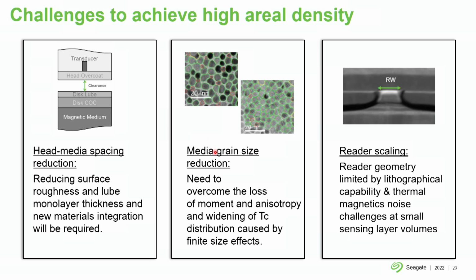Harped about grain size reduction. We have demonstrated 5 nanometer grain size, but it's also a matter of ensuring the distribution and properties are tight, and also the distribution in grain size is tight. And again, that's a very active research area in our recording media design center. And reader scaling is perhaps one of the more concerning issues. If we reduce the size of the reader, which we need to, no matter if we have any other recording technology and if we have very small grains, if we don't have readers that are narrow, we will never be able to keep pushing the track width as much as we want to. So coming up with novel designs to help push these geometries is really key for us.